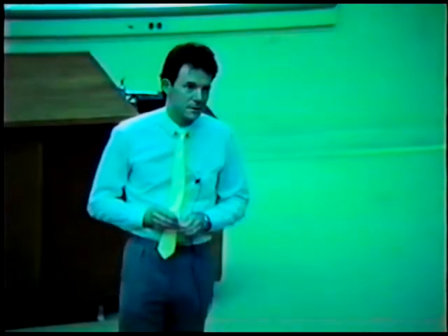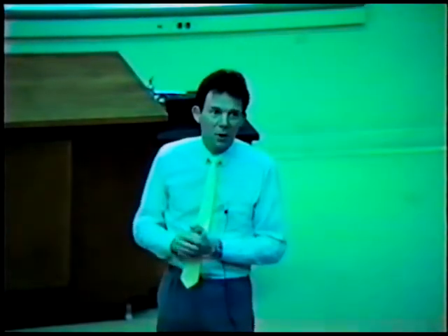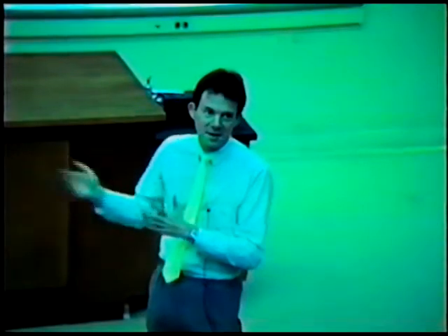Say something about the jump distance per unit jump. Not directly from these experiments. From conventional relaxation methods, you get a relaxation time, and from that, if you do a correlation time, you get a jump distance. But we've avoided that really, because then you don't have to put that into the model. All we know is that over 15 milliseconds, the molecules have moved a certain distance. You could step that back, I suppose.